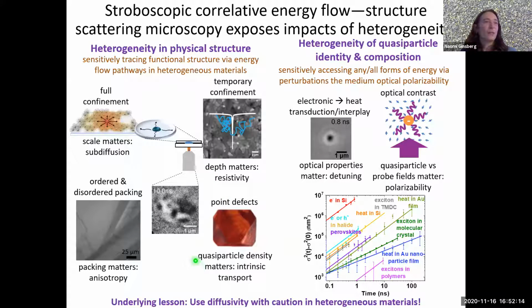We took advantage of just playing around with the population densities of quasi-particles to extract intrinsic parameters, and we also were able to see anisotropies in materials. So that, combined with the fact that by really thinking a little bit more carefully about the optical contrast and how it's generated in our microscopy, gives us information not only about electronic signatures, but also about heat, is super cool to me. And I guess the ultimate lesson of this part of the talk is really that if you're looking at a heterogeneous material, you've got to be really careful to use bulk parameters like diffusivity.